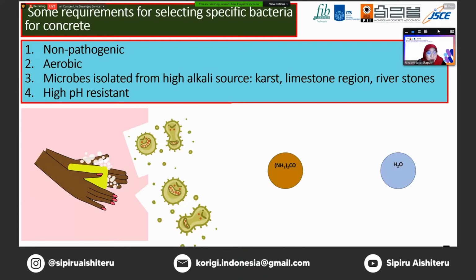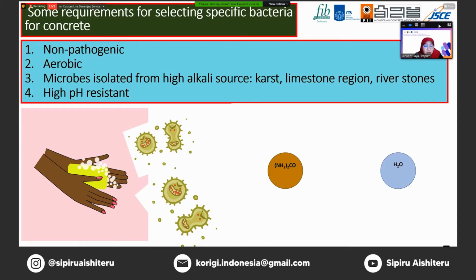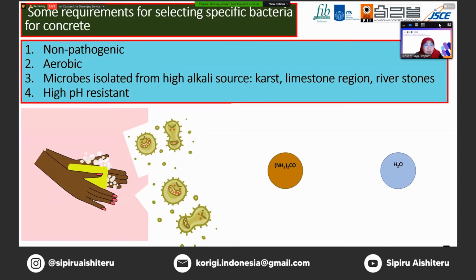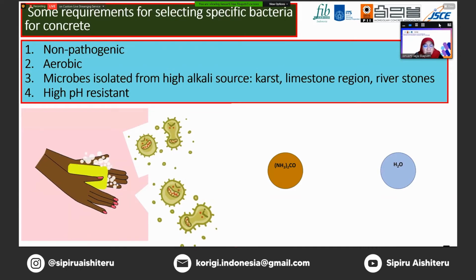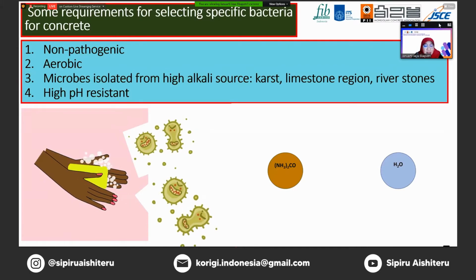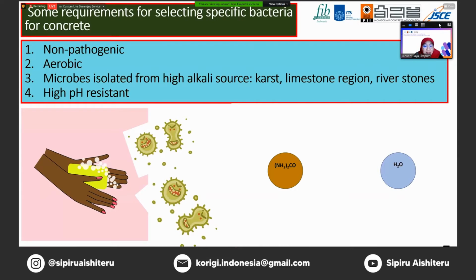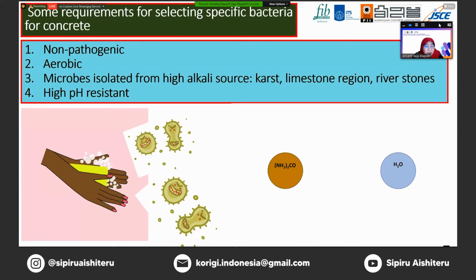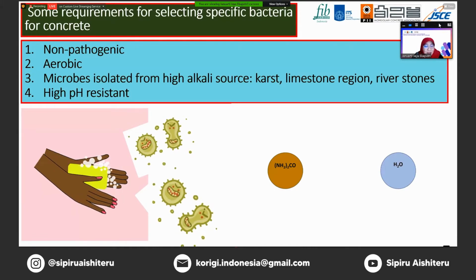I have to emphasize the microbe selection. Obviously, we have to use non-pathogenic aerobic bacteria. We don't want to get sick because of this kind of bacteria. It has to work to fill the pores if oxygen exists. As concrete containing lime, the pH may be a bit higher, and the microbes have to withstand high alkalinity. So we isolated the bacteria from a lime source, a very local place in East Java.